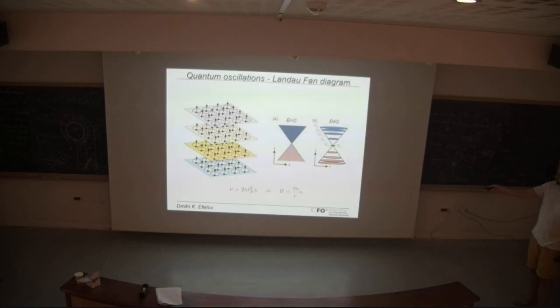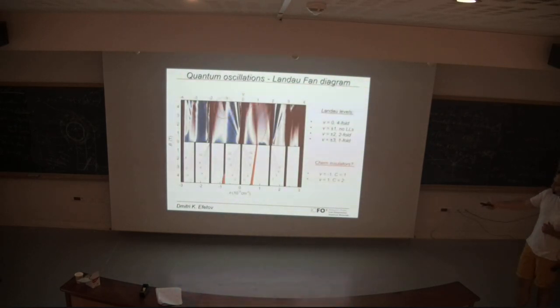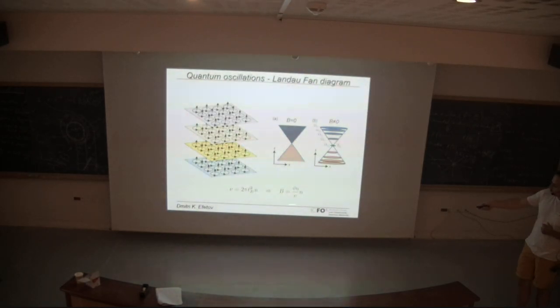I'll try to explain this in this picture. Landau levels are formed in the system, and if you start with a Dirac-like equation, then by applying a finite magnetic field, you break the system into discrete Landau levels, which all have different energies. The number of electrons in each Landau level is determined by the size of the magnetic field. If we apply a higher and higher magnetic field, more electrons are occupied per Landau level, and this relation is, surprisingly, exactly linear with B field.